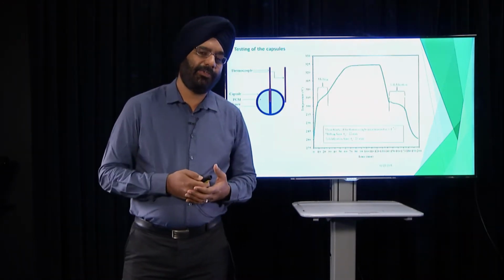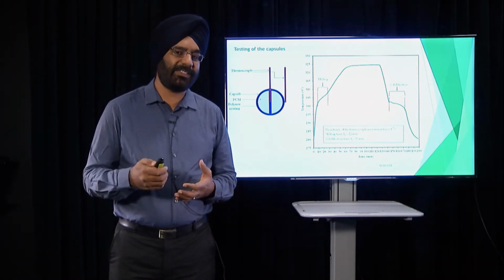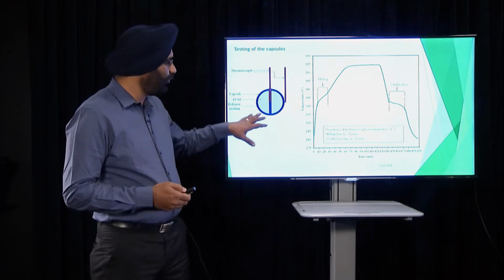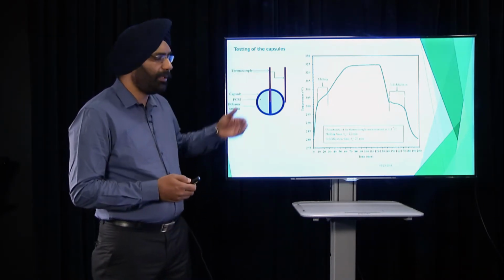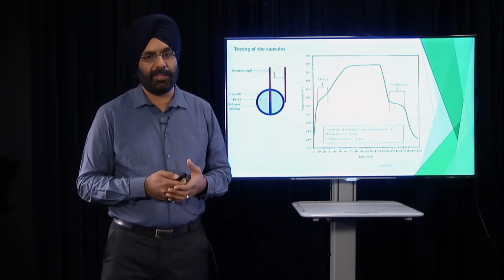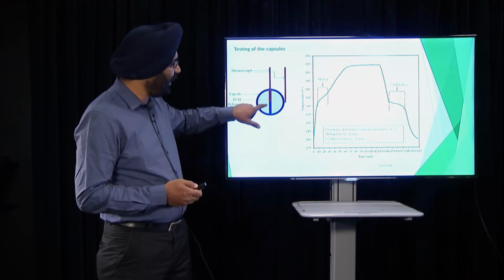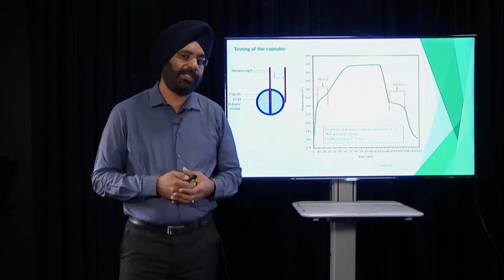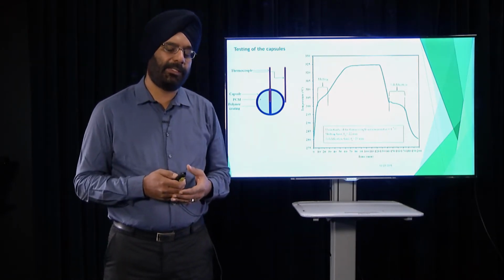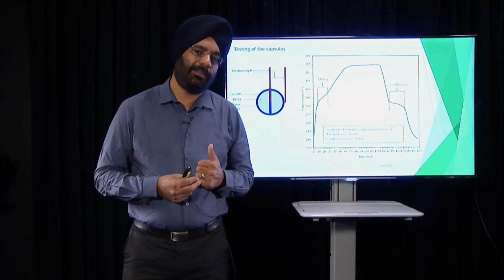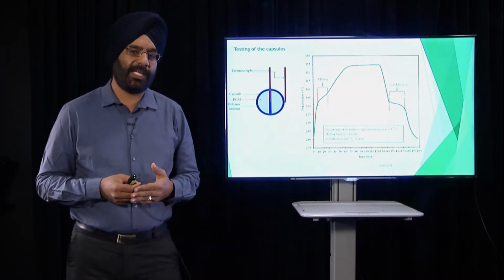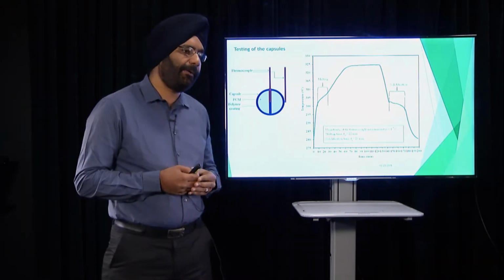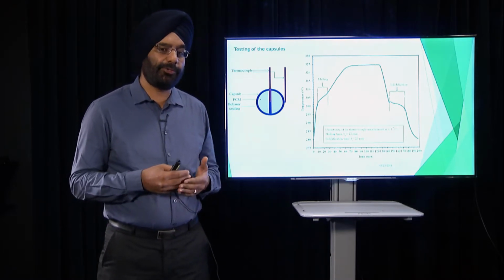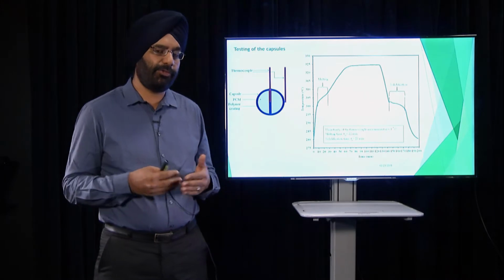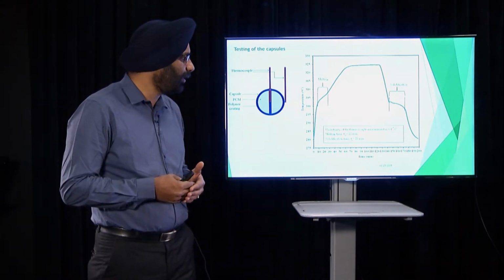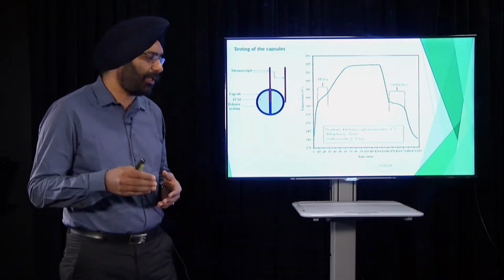So once we fabricated those capsules, the next step is the testing of those capsules. The capsules were tested by inserting a thermocouple, which is a device which measures temperature. There is a thermocouple in the middle of the capsule, and there is also a thermocouple at the boundary. We wanted to see at what temperature the phase change material melts inside the capsule, how long it takes for the capsules to melt under certain conditions, and how long it takes the capsules to transfer their heat back to the heat transfer fluid. All those things need to be determined in order to further test these capsules. So I will be talking about that.